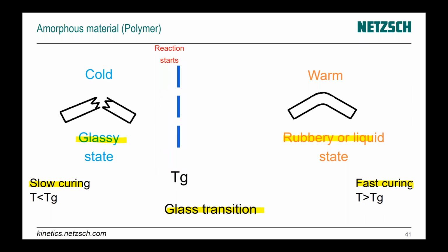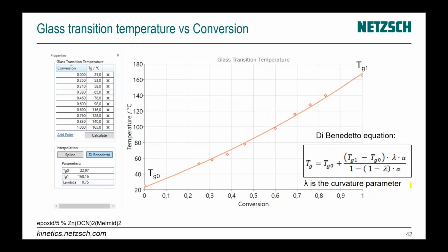A problem is that during curing, glass transition is not in the same position - it changes from a low value to a high value. Therefore, during our modeling we must first find what is the glass transition, and whether our material is below or above glass transition, and if our reaction is slow or fast.